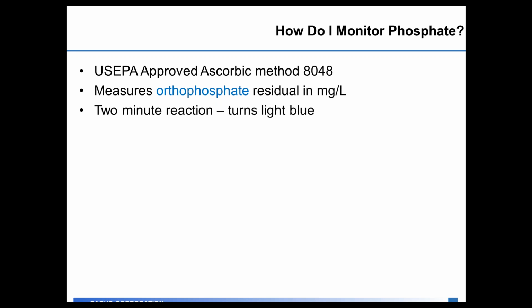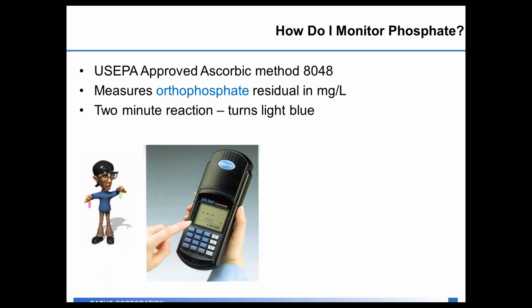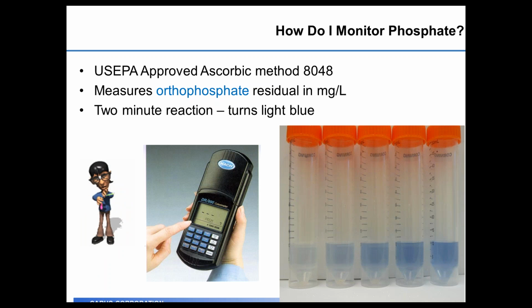In addition to measuring the levels of phosphate that you're feeding out of your tanks, there's also ways to measure the phosphate out in the distribution system. We typically at Carus use the US EPA approved ascorbic acid method 8048, and it measures orthophosphate residual in milligrams per liter. It's a very easy test. You add the powder pillow, you wait for 2 minutes, and the sample turns light blue. The darker the color becomes, the higher the level of orthophosphate that you have in the system.